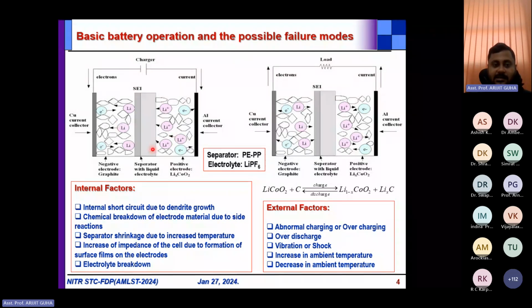As I said, these are the primary reasons. Because of that, the charge storing capability of the battery has reduced over time, and therefore maybe the battery will last for say 5 hours or so. That happens due to repeated charging and discharging of the batteries, and it also depends on the rate at which the battery has been charged. There are different kinds of chargers available, and the degradation of the battery also depends on the rate of charging and rate of discharging. That is also a very important factor. And we also have to see that the battery does not get overcharged or over discharged.